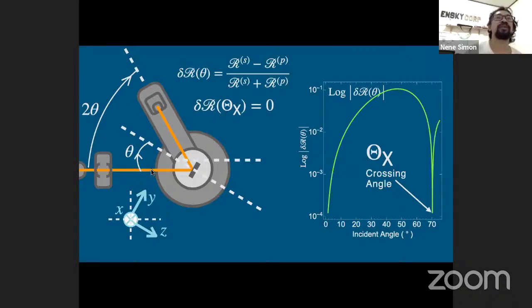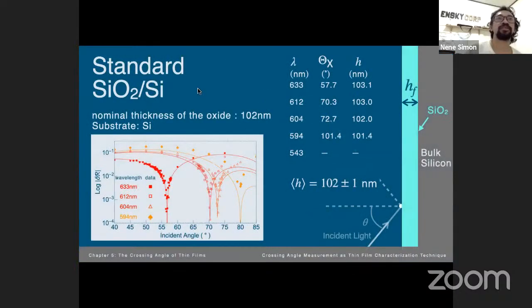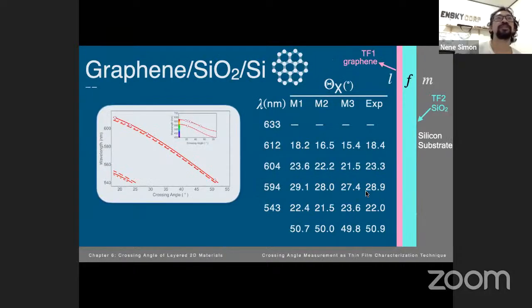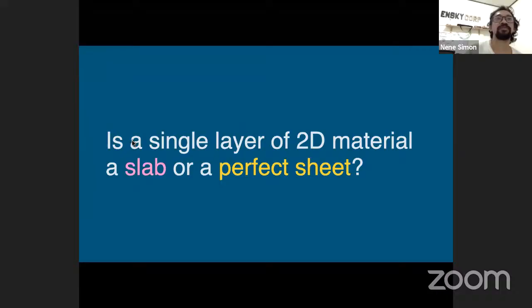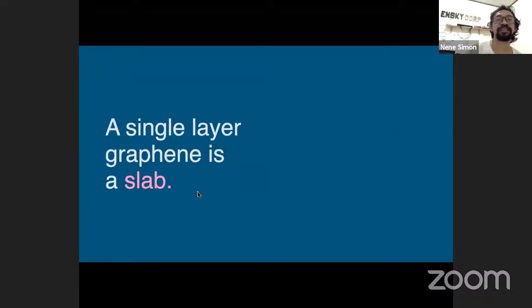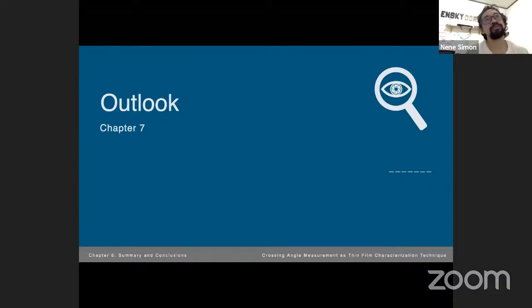And we constructed our experimental setup, and then we calculated the crossing angle from this equation. We measured that the uncertainty for measuring oxide thickness is plus or minus 1 nanometer. And it can also be used to determine the nature of graphene, which is this, our graphene. And according to our experiment, the graphene is best described by a slab.